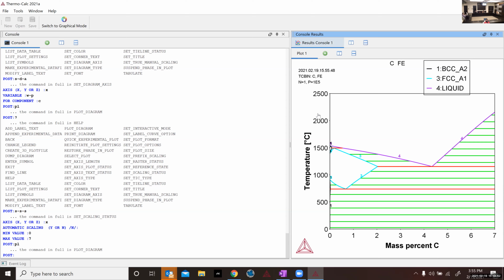Why are we plotting it all the way up to 2,500 degrees and all the way down to 0 degrees Celsius? I will tell you that ThermoCalc is based on primarily experimental data for phase equilibria between solid phases. We typically are not going to have experimental data down at 0 Celsius. So with ThermoCalc, and the way that the free energy functions are defined, anything below right around 0 Celsius is going to get fairly inaccurate. I will tend to use the free energies of the primary phases like BCC, FCC, HCP, maybe liquid, but not so much liquid, but the primary solid phases